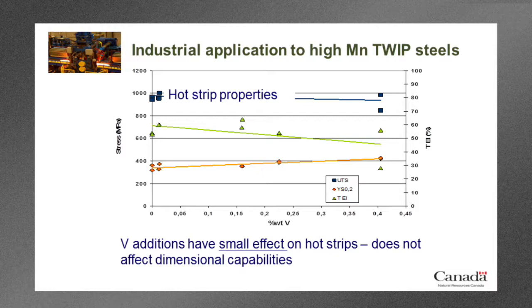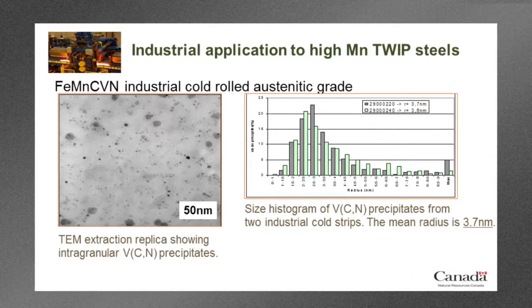You couldn't do this with a different precipitate like niobium or titanium, because they're much less soluble in the austenite. After the cold rolling and annealing step, what we found was some very interesting properties and a very interesting precipitation microstructure. This is a TEM extraction replica, showing a very fine distribution of homogeneous vanadium carbonitride precipitates, and they're very small. You see occasionally larger precipitates, but they're actually in the minority.